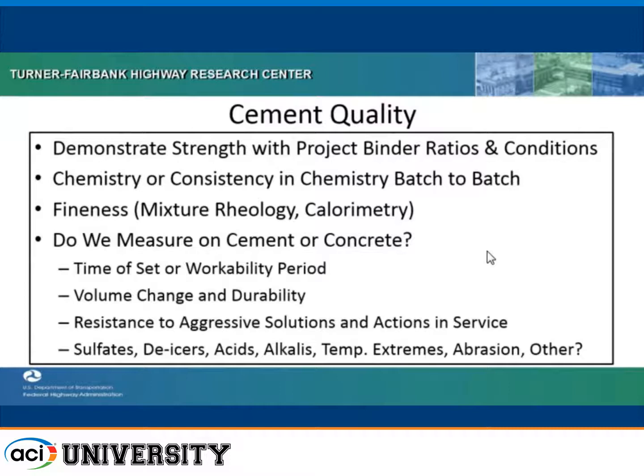There needs to be some sort of consistency in the chemistry of the cement from batch to batch. I assume in most cases we're talking about a powdered cementitious material, so we're going to have to measure its fineness and the rheology when you mix it with water and whatever admixtures you're going to need. And certainly time of set, workability period is important, volume change, durability, resistance to aggressive solutions. Things like sulfates, de-icers, very important.